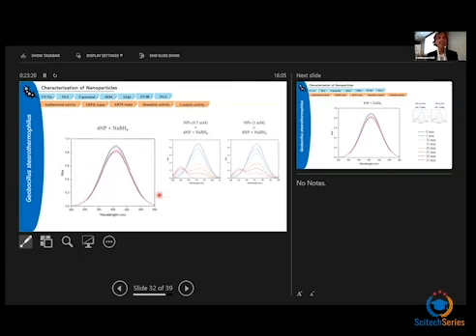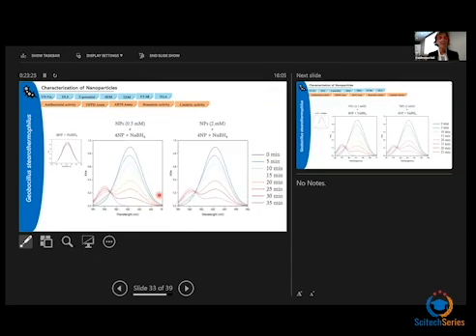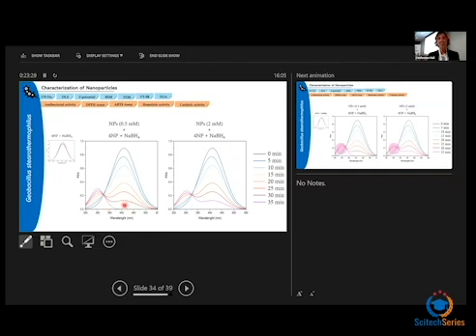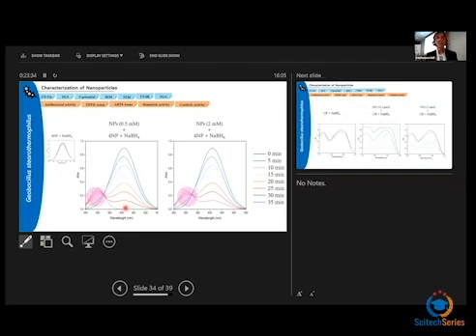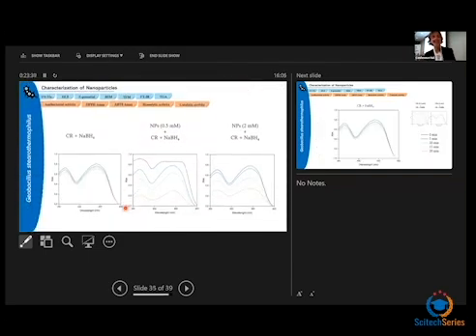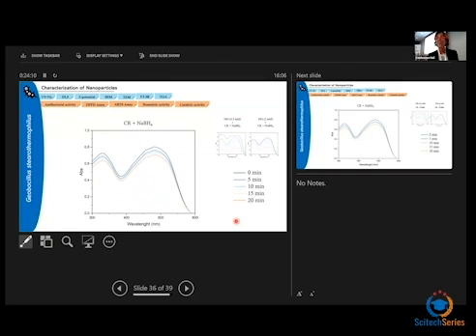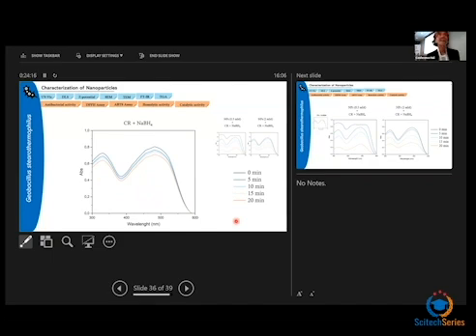Very similar results were also obtained. As shown, we could observe the complete degradation already within about 30 minutes using both kinds of nanoparticles. Very similar results were obtained when using Congo red as the toxic compound. Also in this case, we could observe a lower peak corresponding to the complete degradation of the compound, but it was also visible by naked eye observation, as Congo red is red, and the solution became very clear in half an hour, confirming the strong catalytic potential of these nanoparticles, which can then be assessed for their use in the degradation of toxic compounds in wastewaters.